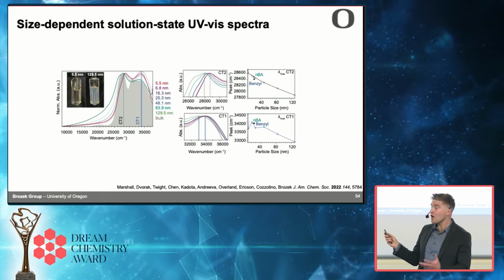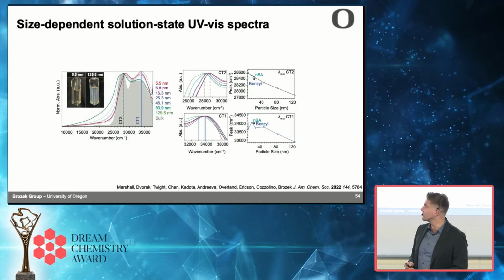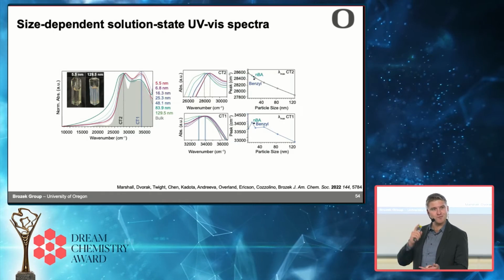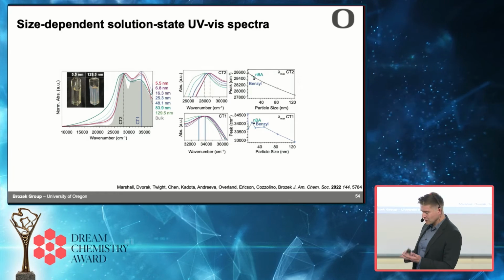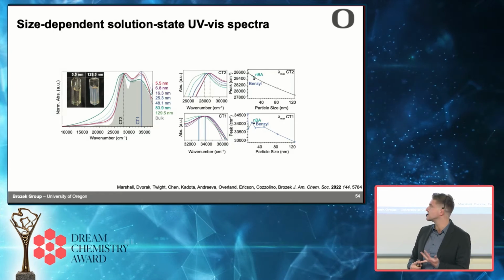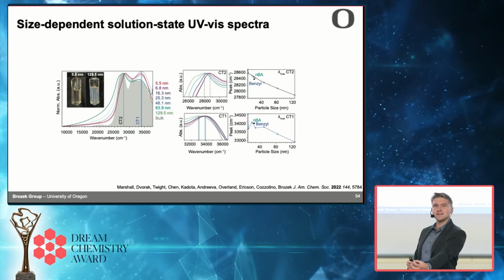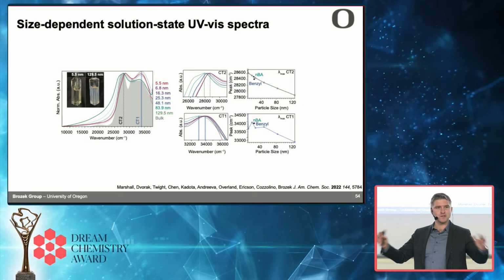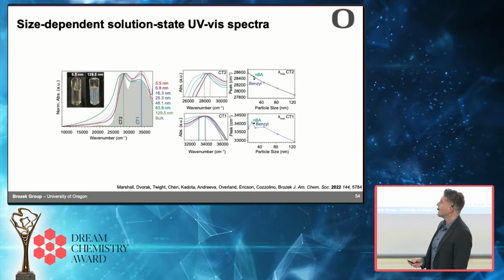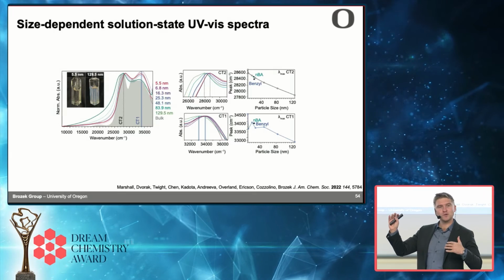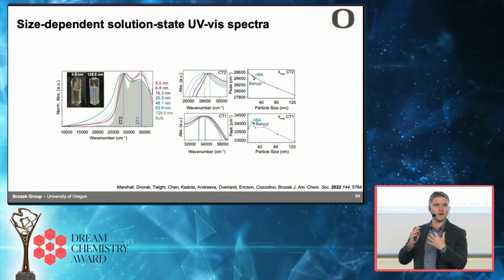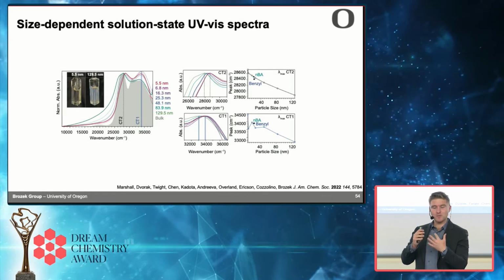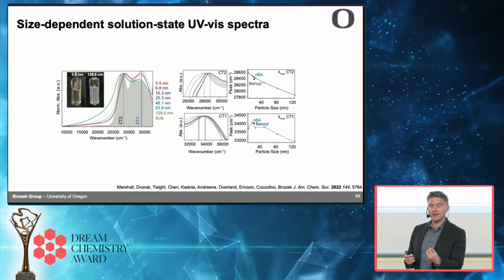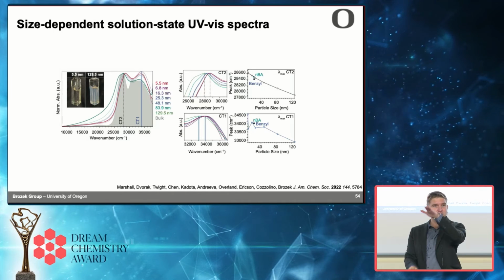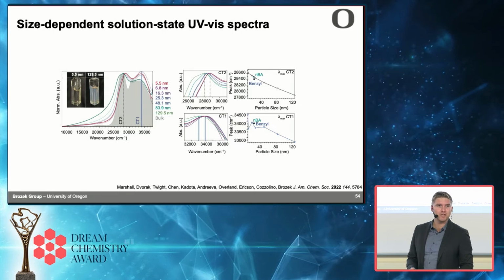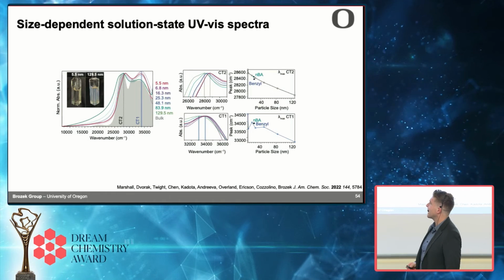But what we think, so we don't know still what is really the root of this, but we're working with computational collaborators and experimental collaborators, and what it's looking like is that something conceptually related is happening. You have orbitals on the inside of your particle, you have orbitals on the outside, you have all your surface orbitals. And as you make your particles smaller, those two types of orbitals communicate with each other more and more, and they destabilize each other. And so by the time you have a 6 nanometer particle, you've really destabilized those orbitals, and you get this bigger HOMO-LUMO gap, and everything blue shifts. But that's just kind of our best guess right now.